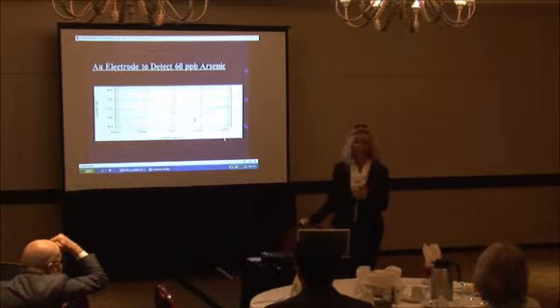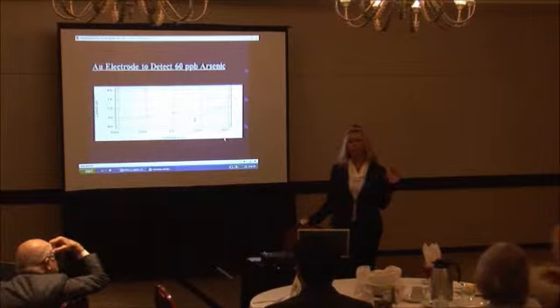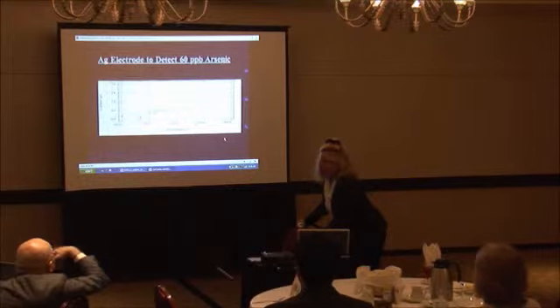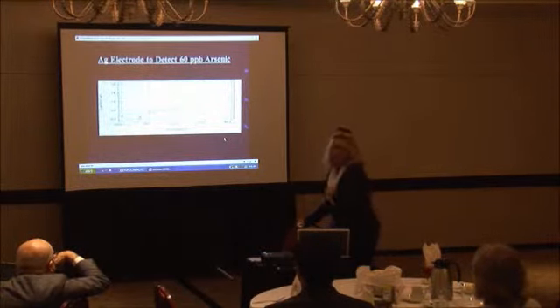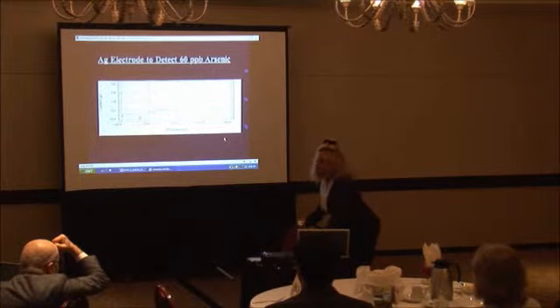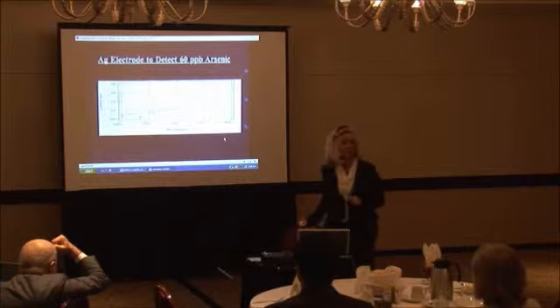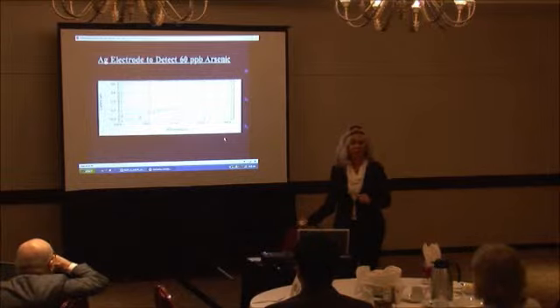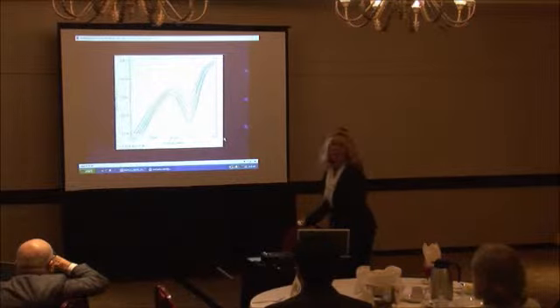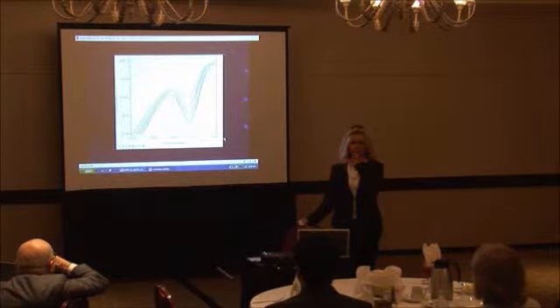And I wish I would have shown you some of the results so you could see why the student had to realize that gold was the metal of choice as opposed to platinum or carbon for arsenic, because when you read the literature, they talk about gold plating. So when you give them those different electrodes, they have to explain why gold is better. You see why it's a little more problem-based? And then there is an example of the arsenic on silver. So can we see the silver is not detecting as well? This is on gold back here, and this is on silver. So the peak is not nearly as nice, is it?